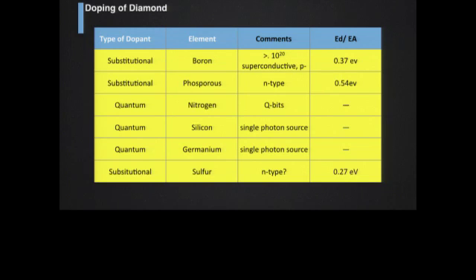So you need boron and phosphorus. Of course, boron makes it p-type, phosphorus makes it n-type. These are the activation energies associated with that. And you'll notice that instead of being a few meV, which is the case for silicon, these are about a half or so of an eV, which means that they're not 100% ionized at room temperature.